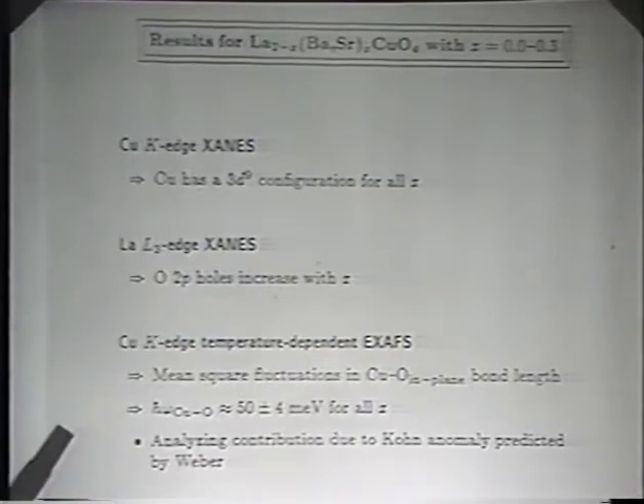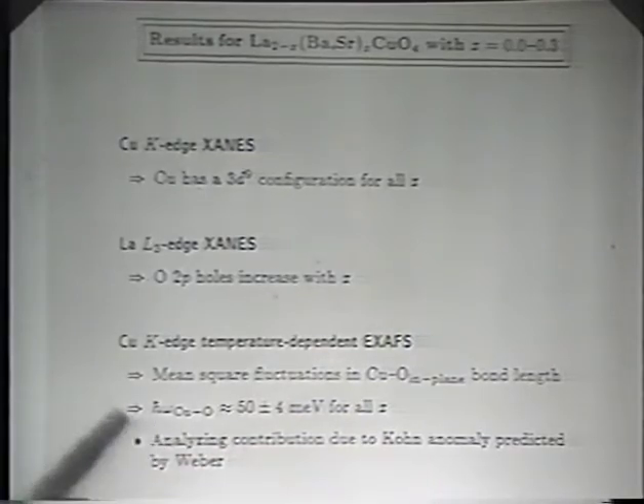And then quickly from the copper K edge, we've measured mean square fluctuations in the copper-oxygen bond length from the temperature dependence of the EXAFS. Fitting that with a simple Einstein model, we get a characteristic frequency for the copper-oxygen vibrations of 50 plus or minus 4 millielectronvolts for all x. We don't find any variation. And this fluctuation includes lots of other modes, but it includes the breathing modes, which supposedly would soften if electron-phonon interactions are important.